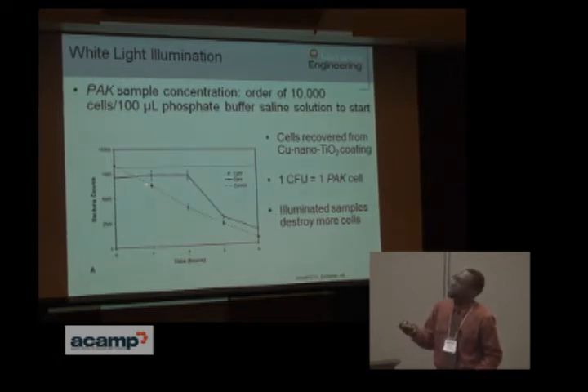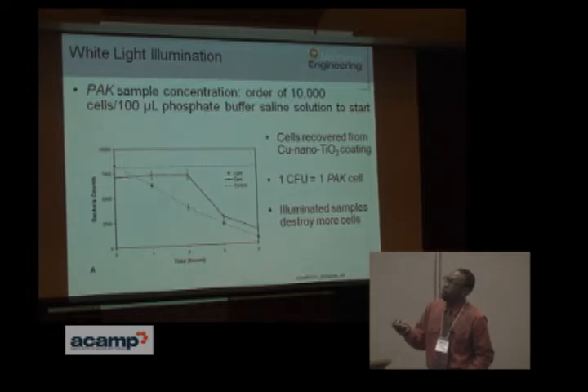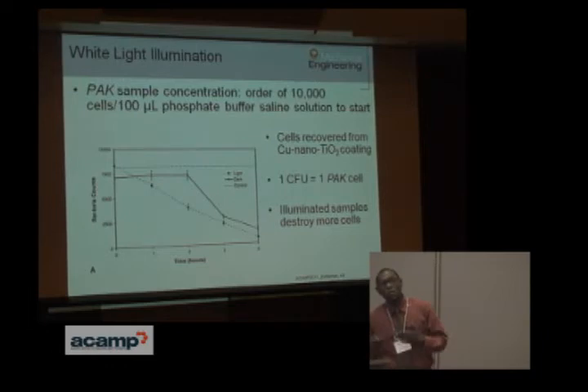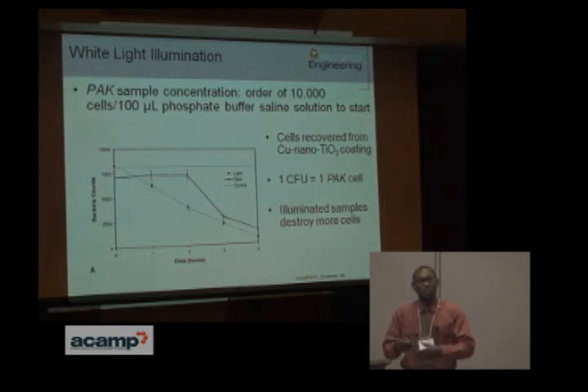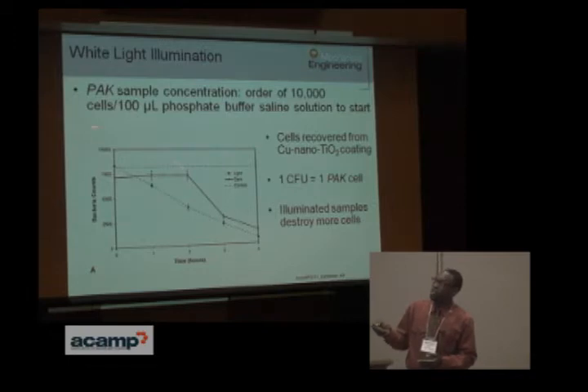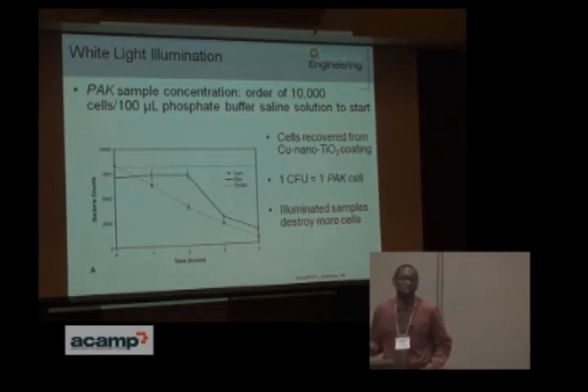Now, as you can see very nicely, we do get significant decay or destruction of bacteria as the time passes. As you can see, we do have less destruction of bacteria whenever we hold the samples in the dark chamber. And you do see some weird things going on with the curve here. This is indicative of the fact that because we're not killing bacteria fast enough in the dark chamber, we are having some difficulty recovering all the bacteria from the surfaces, so then our error tends to increase. That's the reason why I wanted to show this, because it shows some of the issues that occur as a result of working with the dark chamber in terms of the destruction of bacteria.